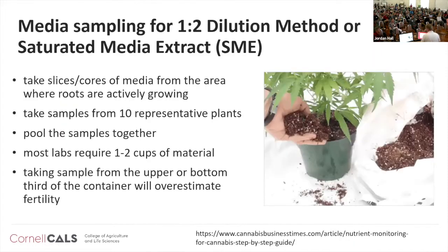And analyzing. With the 1 to 2 dilution method, or if you send a sample to a lab for the saturated media extract method, you're taking slices or core of the media from where the roots are actively growing. So we find that salts can build up at the top surface as well as the bottom. And so we want to take samples of soil from the middle of the container where the roots are actively growing. You would take samples from 10 representative plants, pool those samples together. If you're going to send in a sample to a lab, talk to the lab, but they'll usually require 1 to 2 cups of material.